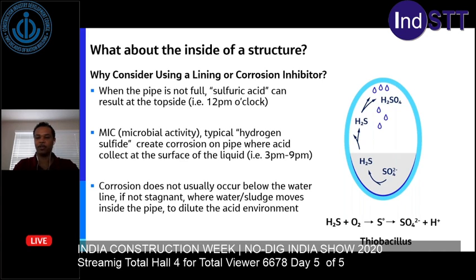So when your pipe is not full of product, like the picture depicts, you can see at the 12 o'clock position, you may have corrosion occurring due to sulfuric acid at the top side of your pipeline. Also, the pipeline shows the product is around the 3 to 9 o'clock range. You may have some hydrogen sulfide occurring on the sides of your pipe. And the bottom side, around the 6 o'clock position, you typically don't have any corrosion occurring as long as those acids are being constantly moved and flushed away. But if you do have a no flow or stagnant condition, you can have bottom side corrosion occurring.